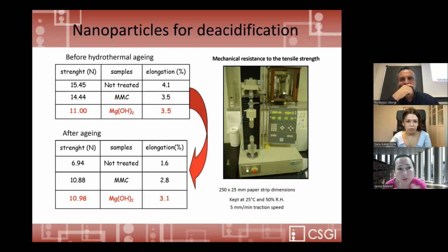But usually we don't have only rag papers, we have some application of ink and pigments, and mostly machine-made paper containing lignin. When I tried to spray your particle dispersion on the lignin-containing samples, I ended up with yellow dots, because it takes quite some time under room conditions to change from calcium hydroxide to calcium carbonate. And this time is really problematic, because you can end up with discoloration of the paper artifacts.